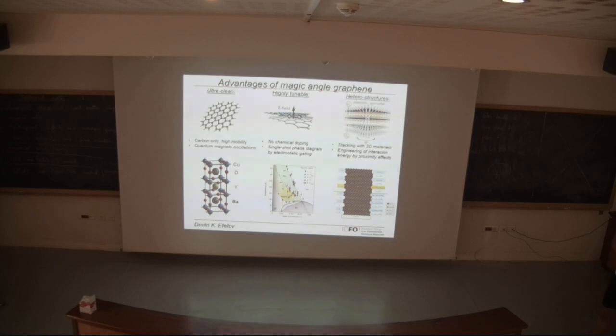Okay, just to contrast these properties with cuprates, for example. As I said, graphene is carbon only, so it's really just one element. Compared to the cuprates, you have very complicated unit cells with many different atoms and so on. This is about the high tunability. This is a typical phase diagram one obtains with YBCO. As you can see, every data point here is one different crystal. So one needed to grow, I would say, 20 to 50 different crystals just to obtain a phase diagram like that. In graphene, you can do it all in one device.